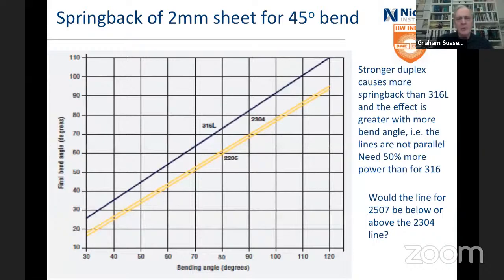Just a couple of mechanical things. Put 2 millimeter sheet and you're trying to bend it 45 degrees. And here we've got the curves so that you read off what you actually are aiming for and what you've got to actually bend it to. Okay, and it's different for 316, 2304, 2205. And if we had 2507 in there, just think about where that would be, because looking at it, you've got to bend the 316 about 50 degrees, the 2304 and the 2205, you've got to go about 62 degrees.